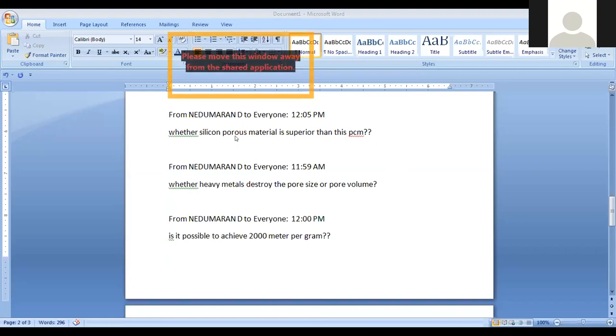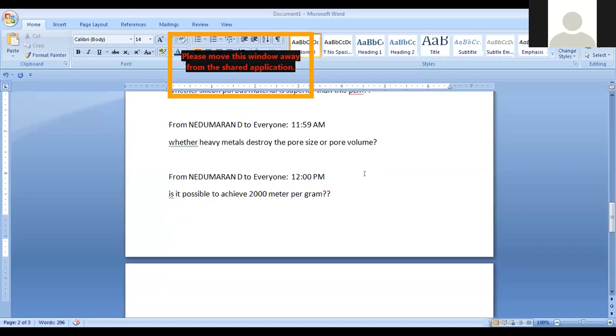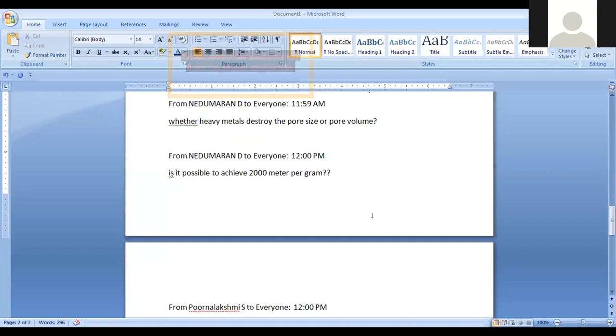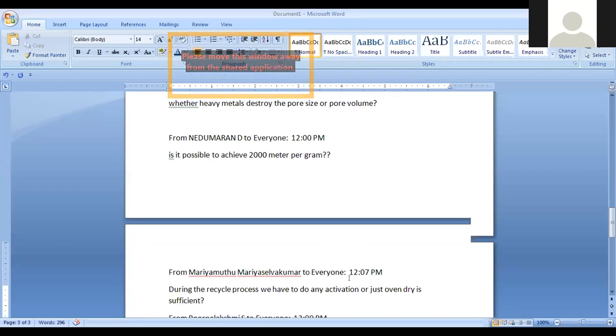Okay, thank you. So is silicon porous material superior? Silicon porous material, not superior, because sometimes we need to use acid in the reaction mixture. The silicon comes out as silicon dioxide or something. So corrosive nature happens when using silica. But carbon is not corrosive in acid-based treatment. That's why carbon is very stable in acid and base conditions, and also at high temperature. If you mix it with air, only carbon dioxide and carbon monoxide are liberated. Otherwise, carbon is highly stable. But in the case of silicon, if mixed with some acid or base, it completely dissolves or converts into another form. So that's why we need to avoid silicon and use only carbon.